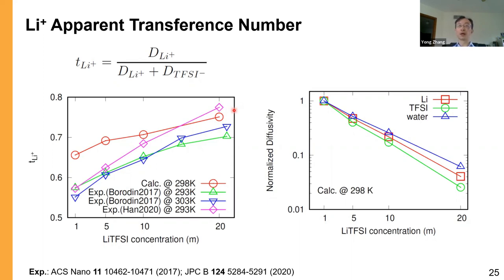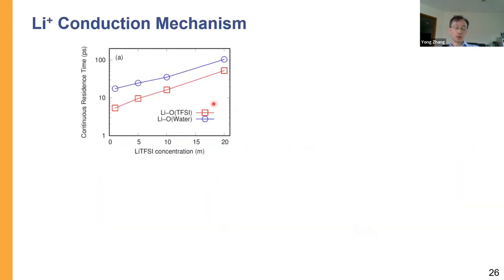Then the next question will be, in this two-domain picture, they are kind of thinking lithium is solvated by water and really easy to conduct in the water-rich domain using this so-called vehicular mechanism. So what would be the dynamics? What's the mechanism here in our picture? Here I show you the residence time between lithium and oxygen from TFSI and between lithium and water. You can see it is several picoseconds, depending on the concentration, up to 100 picoseconds.